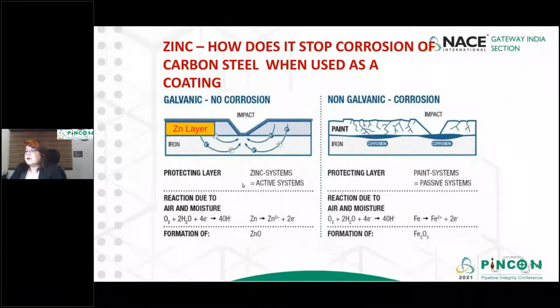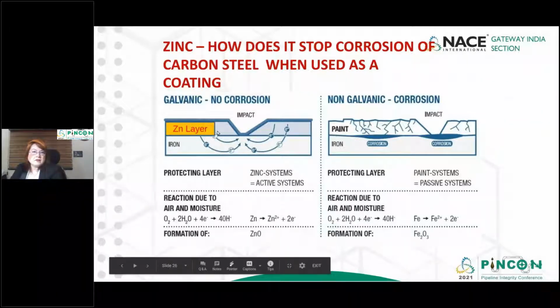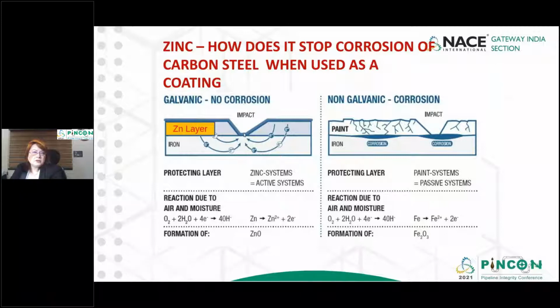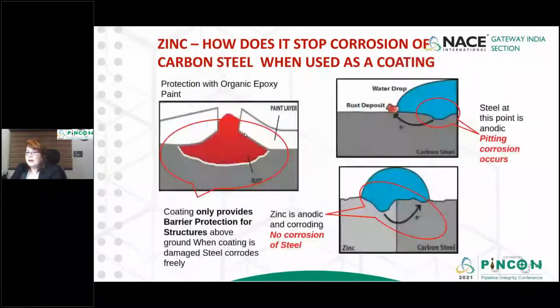Whereas in zinc metallic coating, zinc oxide forms an active layer and protects the structure. So with the formation of zinc oxide, it protects the layer, the electron passes from the zinc layer and it protects the affected part. So there is no corrosion. And as you can see, zinc stops corrosion of carbon steel when used as a coating, as against organic epoxy paints.